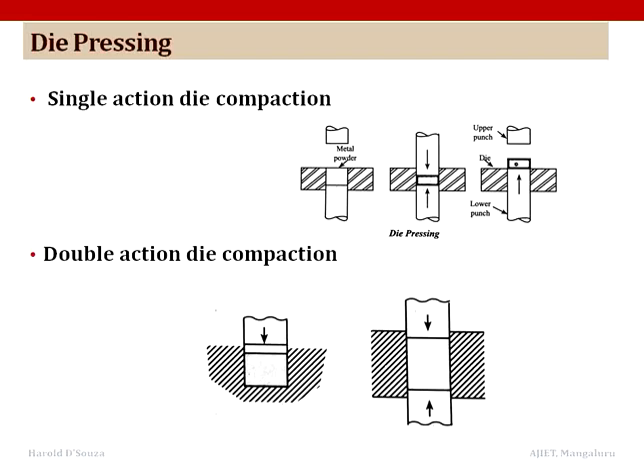Here the powder is compacted simultaneously from the opposite direction by both the top and the bottom punches. Equal or different amounts of pressure may be employed from each direction. The die table remains stationary and the upward movement of the lower punch ejects the part out. Now, this technique can be used for manufacture of thin walled bushings and cylindrical bearings.